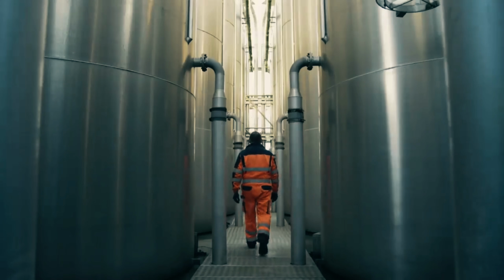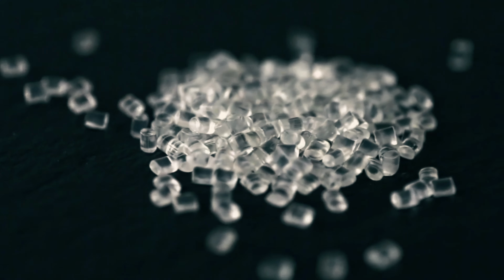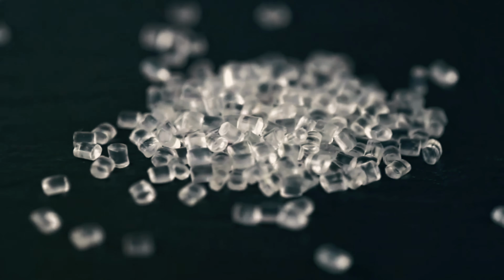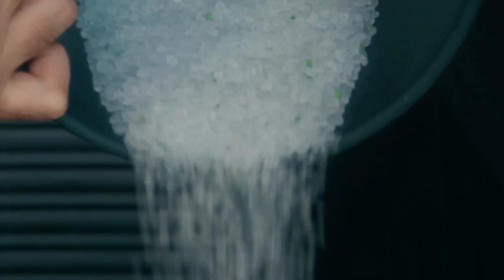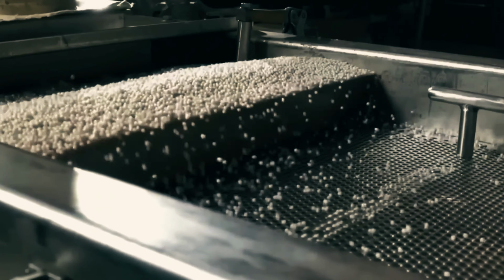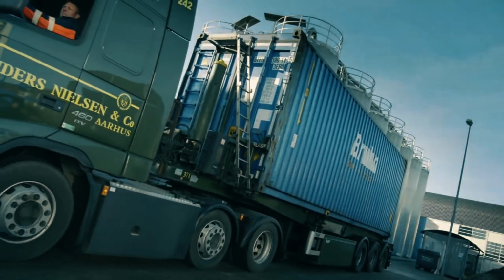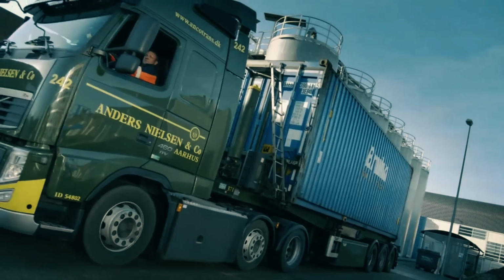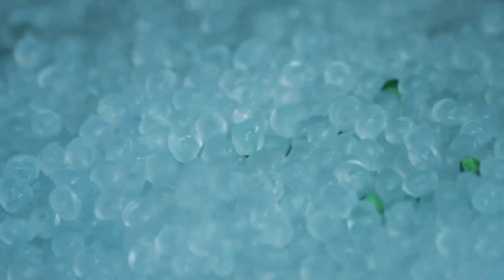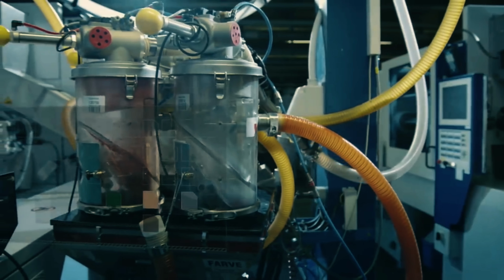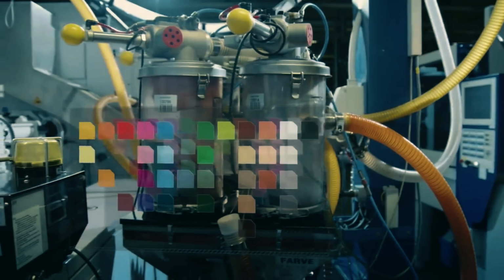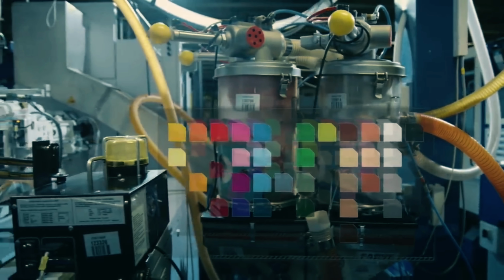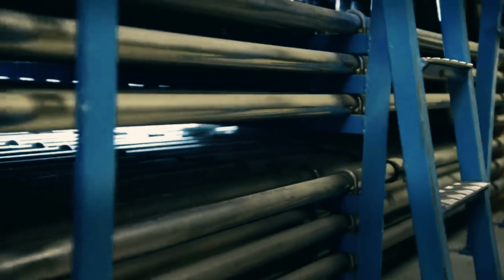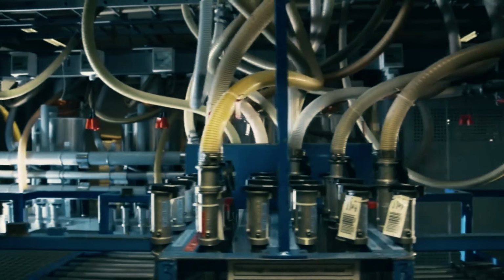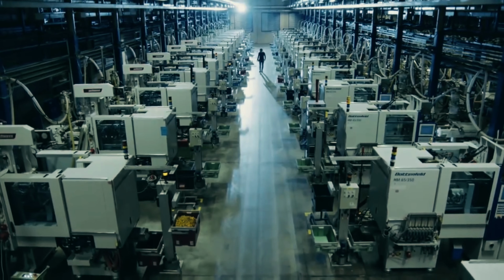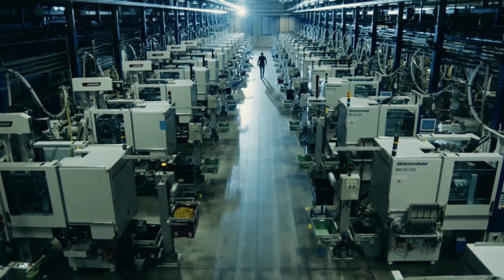Most toys start with a different plastic than bottles. ABS, or acrylonitrile butadiene styrene, valued for its strength, its glossy finish, and its ability to hold fine detail after cooling. It arrives at the factory as small colored pellets, already tinted to the exact shade needed. Engineers match colors using digital color codes, so a red piece made this year matches one made a decade ago, down to a fraction of a shade. Before melting, the pellets are also dried in large hoppers, since even a trace of moisture trapped inside can create tiny bubbles that weaken the finished piece.